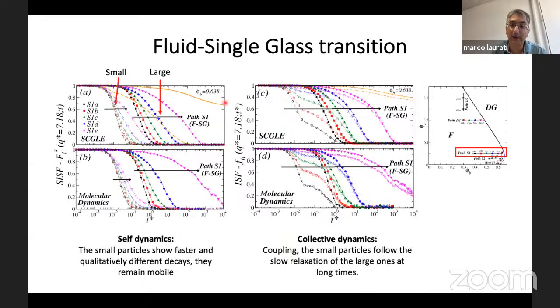Okay, so now I'm starting to show you some results of the theory and the simulations. The first thing that we did was investigating the fluid to single glass transition along a line where we're increasing the fraction of large spheres at constant small spheres. Here you see the self-intermediate scattering function, which tells us about the self-dynamics, the dynamics of individual particles, and instead the intermediate scattering function, which tells us about the collective dynamics of a group of particles, which also reflects the structure of the system.